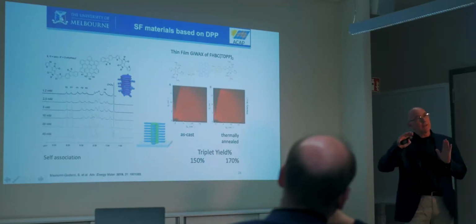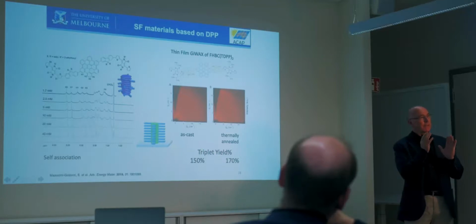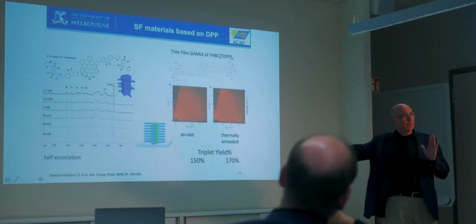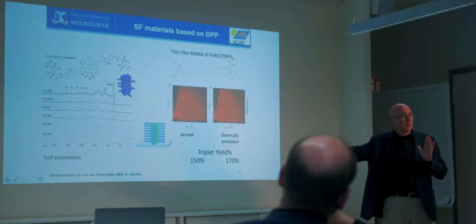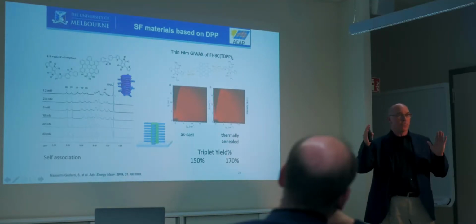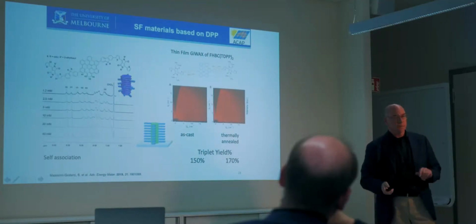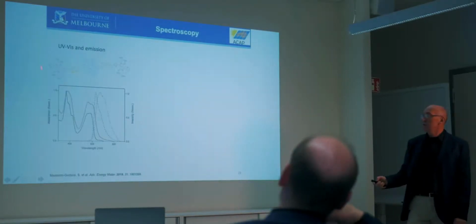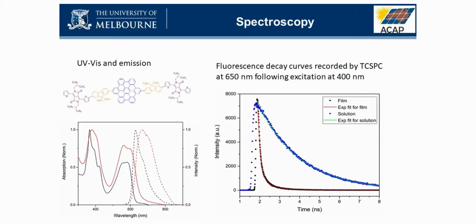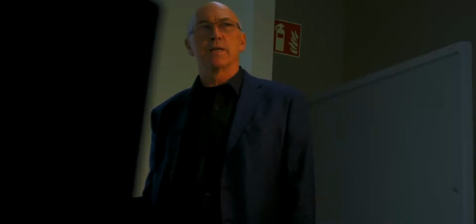However, if you have singlet fission, it means you're taking that singlet state and generating all these triplets, which are going to be lower emissivity, and therefore you should fundamentally change your fluorescence kinetics. These are the absorption and emission profiles for the solution and then thin film for this material. When we look at the fluorescence lifetimes, in solution we don't see a lot of change from the isolated chromophores. However, in thin film, we really kill the fluorescence.